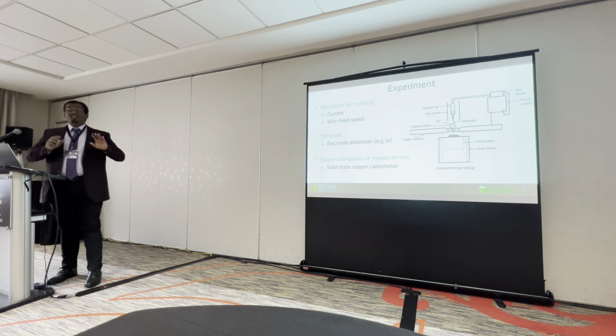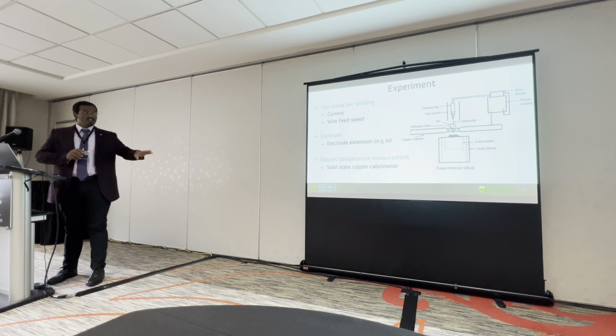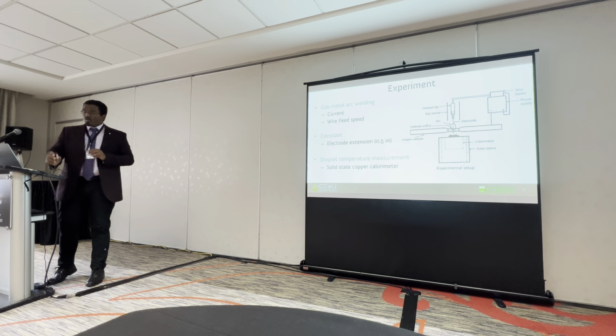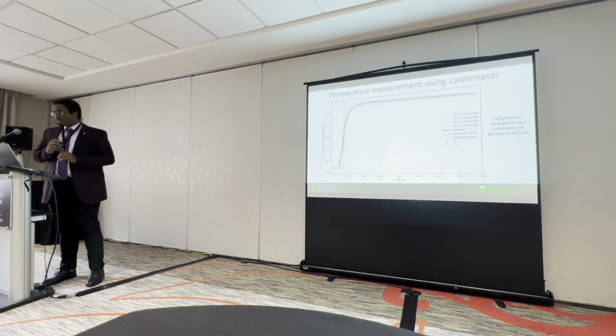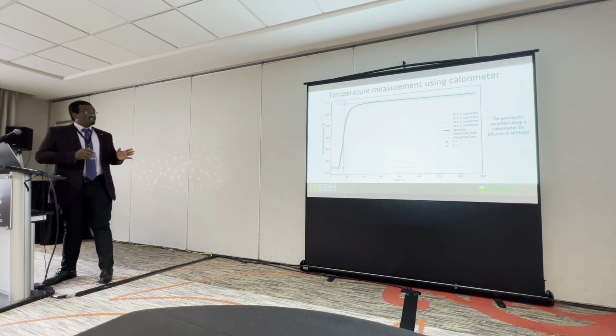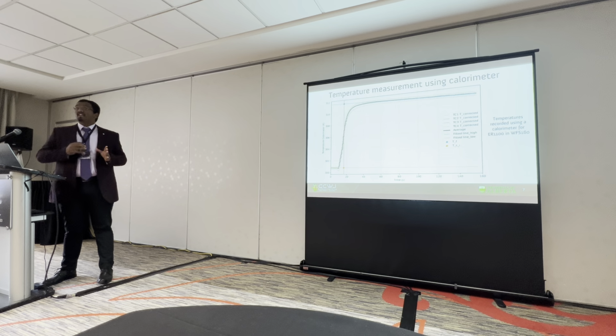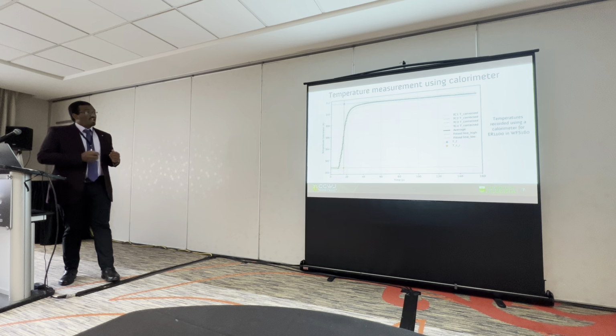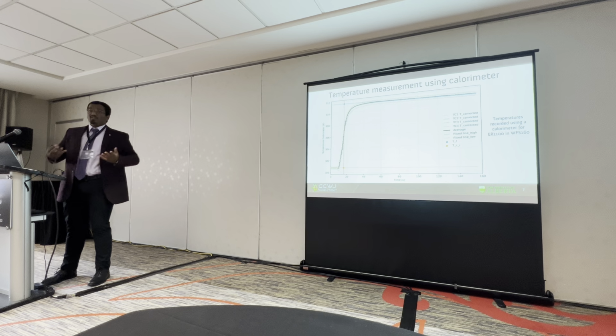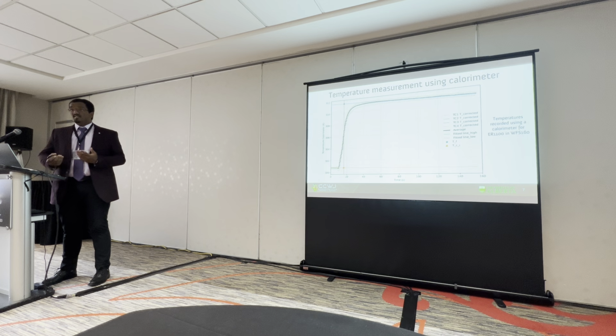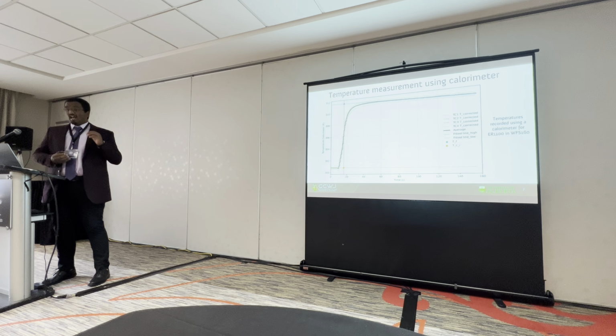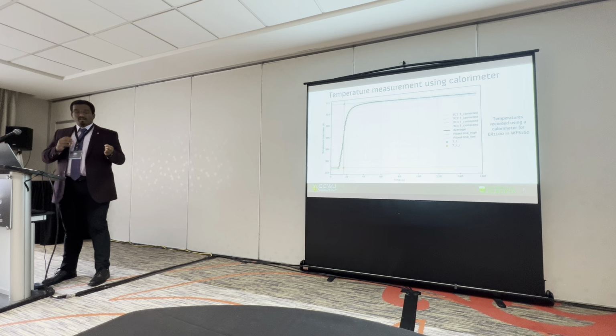Just letting you know, that is not the actual droplet temperature, but just the temperature once the droplet falls into the calorimeter. This shows the results of the calorimeter, the data recorded once the molten droplet falls into it. Because I have 4 thermocouples, I'm able to average the results of all 4 thermocouples to give an actual number, which is a very good representation of the overall temperature of the calorimeter.